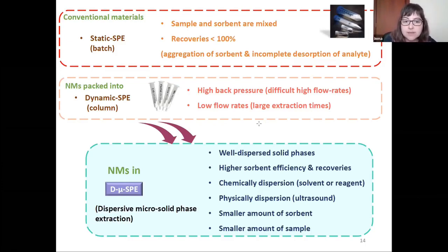Thus, an alternative can be the use of dispersive micro solid phase extraction in combination with nanomaterials, since they are well-dispersed phases that allow higher extraction efficiency, allowing the chemical or physical dispersion by means of addition of reagents or ultrasound energy, using a smaller amount of sorbent and also a small amount of sample.